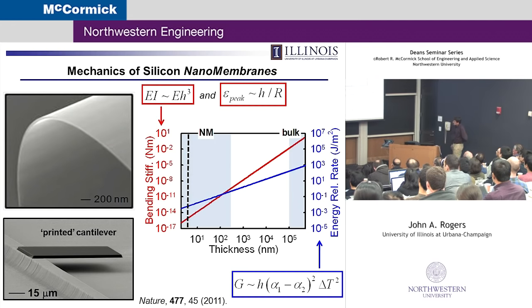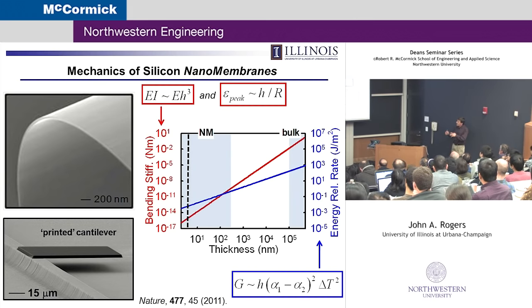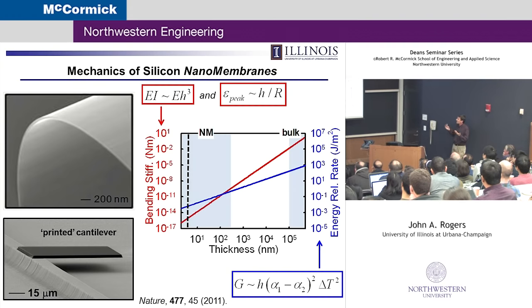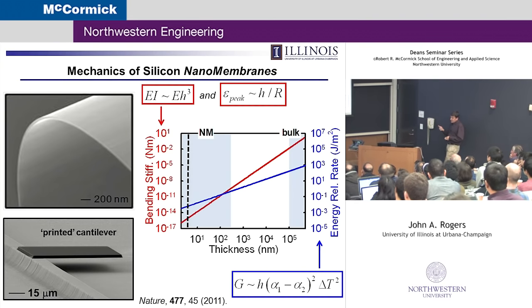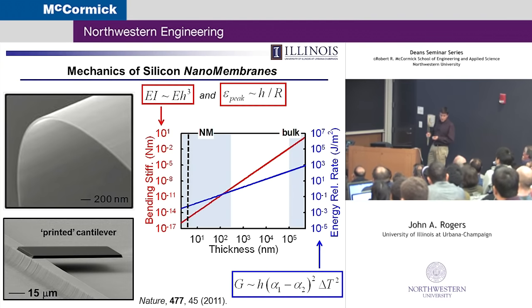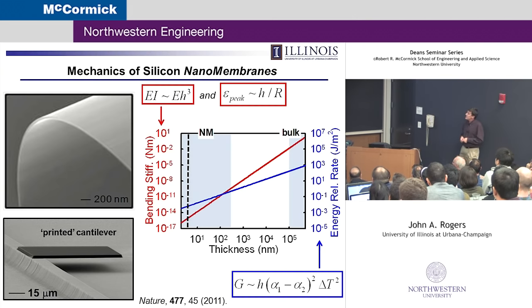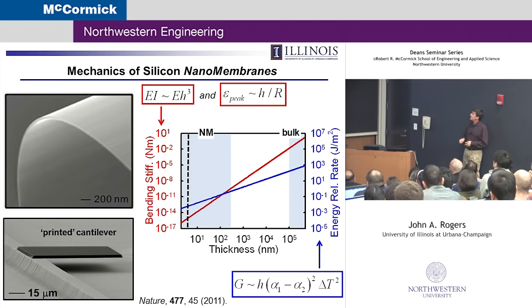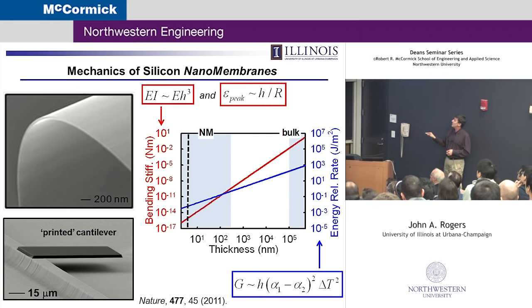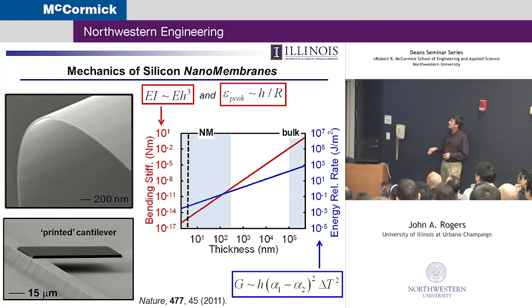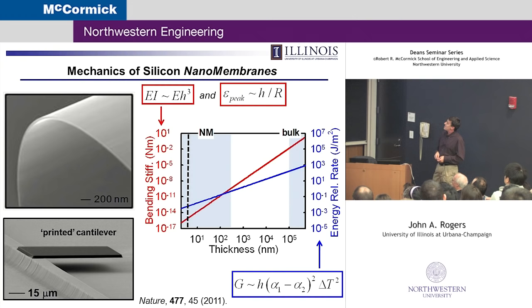So if you think about a silicon wafer, it does have the properties that I mentioned before. It's a plate of glass, essentially. You can't bend it. You drop it, it shatters into a million pieces. That's partly because of the intrinsic properties of the silicon, but it's also partly a consequence of the geometry of the wafer. It's about a millimeter thick. So if you imagine silicon now shaved down into much thinner geometry, so silicon nanomembrane, so think of a sheet of silicon. This is monocrystalline semiconductor grade silicon at about 20 nanometer thickness.